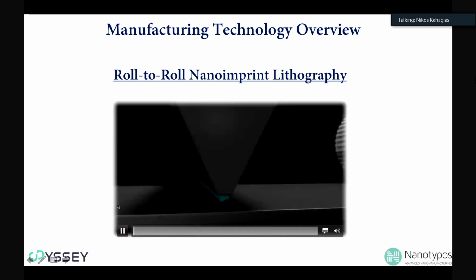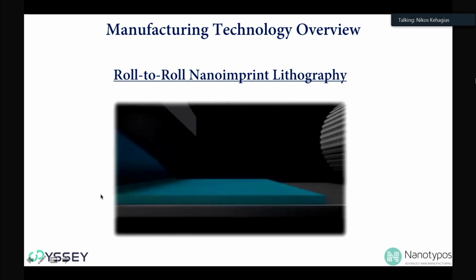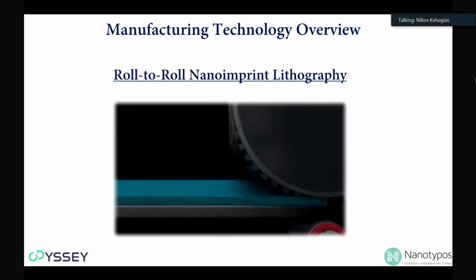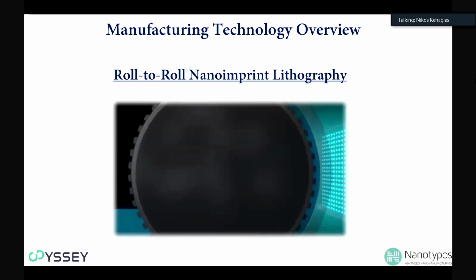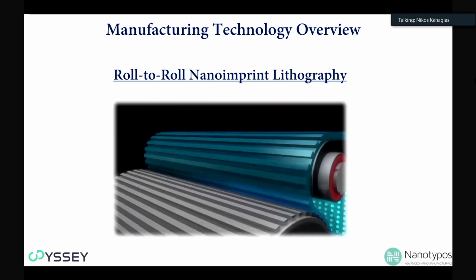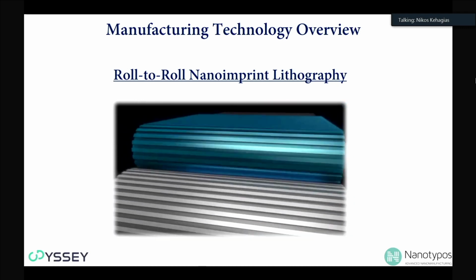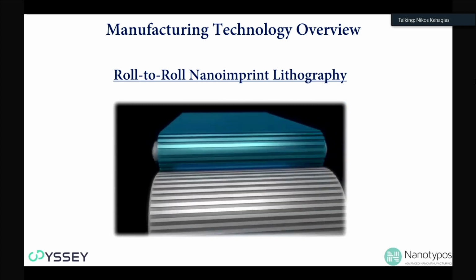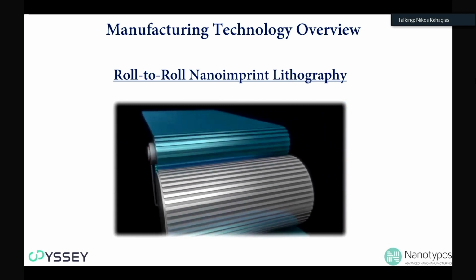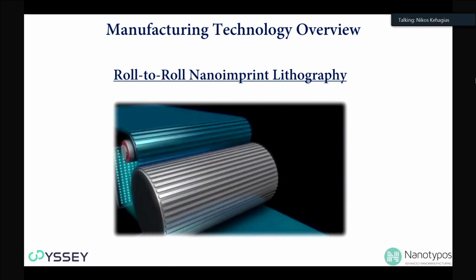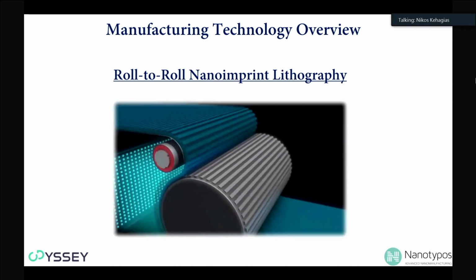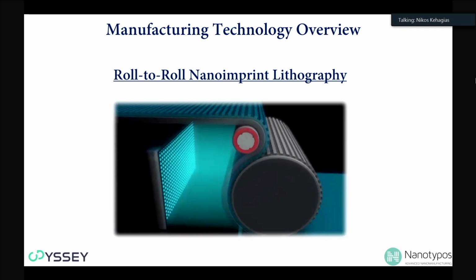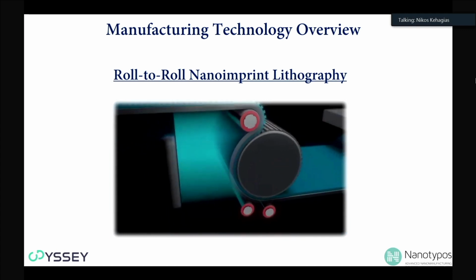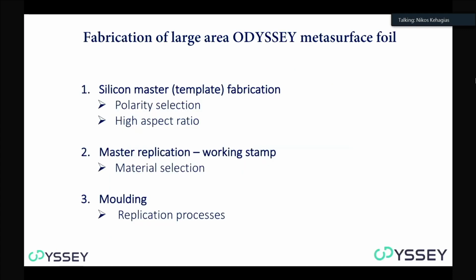The evolution of batch-to-batch nano-imprint lithography is the roll-to-roll. So in this case, instead of having a hard substrate, a silicon or glass substrate, one can use a flexible mold, which is covered over a drum, and in a continuous way replicate the micro nano topographies which are on the stamp on a flexible substrate, again either by temperature or by UV light.